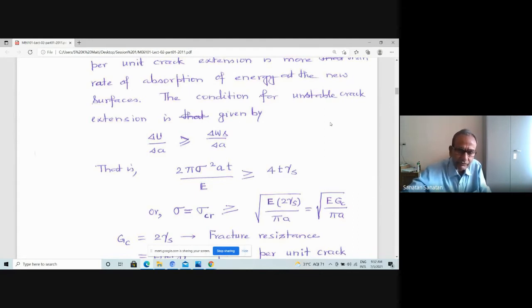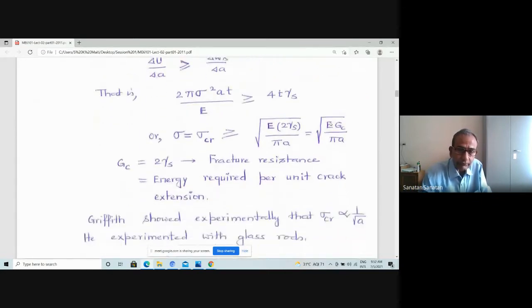It had a similar structure to the classical interatomic spacing model, and this became the actual starting point of calculating the fracture strength of a material with a crack, with a defect. First time it is with a defect. So sigma CR is root of 2E gamma S by pi A, and it was written as root of E GC by pi A. And GC is nothing but the fracture resistance of the material. And what is its value? It is nothing but 2 into gamma S, where gamma S is the surface energy requirement per unit area.